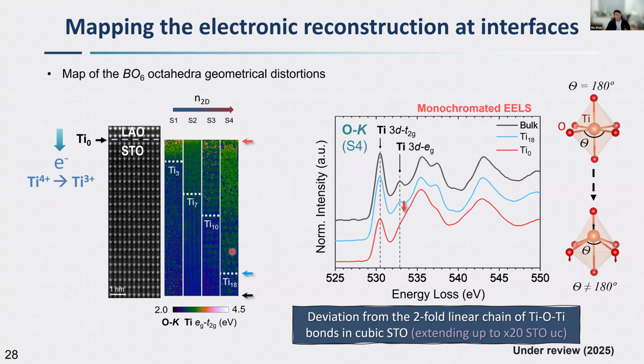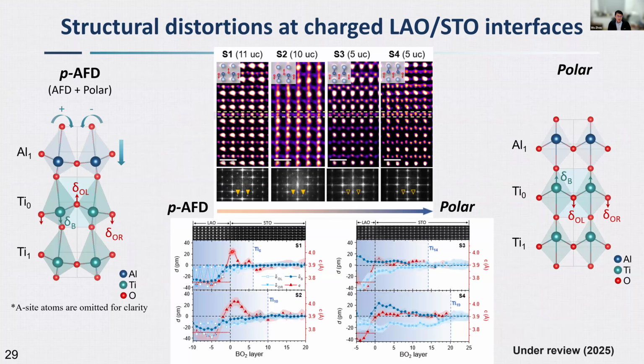So this is from the electronic structural reconstruction. And we can also see it from the atomic structural analysis itself. In the low doping structure, we have antiferro distortion combined with a polar distortion. So you can see the oxygen position oscillating up, down, up. And you can also see this distortion from the superlattice spots.